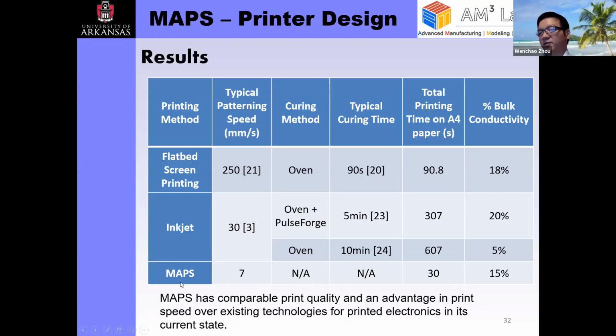So this is our first prototype of the MAPS technology, and we compare printing a single A4 paper. For screen printing, you will take over 90 seconds. For inkjet, you will take a few hundred seconds. For MAPS, you will take about 30 seconds. And the printing quality, which is characterized by the bulk conductivity as a percentage of silver, these are some of the best reported results in the literature, and this is ours, and it's comparable.